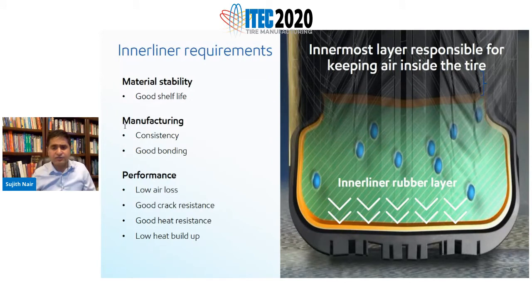Right, so there is a thin layer of rubber, and this is made from bromobutyl, chlorobutyl, or bromobutyl blended with several other elastomers. Some of the requirements for this layer in order to give a good performance in the tire are material stability. It needs to have a good shelf life. It needs to be consistent in manufacturing. It needs to have a good adhesion to the other layers of the tire, so good bonding.